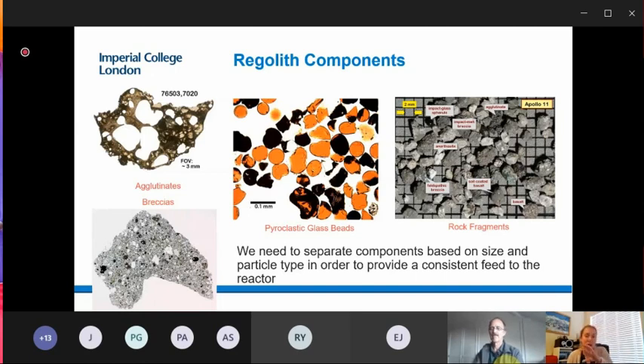So if we have our regolith that is comprised of these different components, then perhaps we might think about separating components based on their size and their mineral type, so that we can provide a consistent feed into the reactor. And this is what we would like to do. So if we take, again, oxygen production by hydrogen reduction, we know that hydrogen reduction targets the ilmenite. So if we were going to use hydrogen reduction to produce oxygen, then perhaps we might like to increase the proportion of ilmenite in the feedstock.